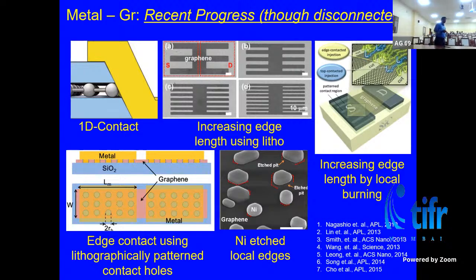Let me also highlight this thread, which later when people had shown that the edge contacts are better compared to the top contacts. While no physical explanation was given, the edge contacts were shown to be better, and of course earlier the low temperature contact resistance was shown to be better compared to the room temperature contact resistance. So the physics world moved into the edge contact and doing measurements at low temperature. Right? I mean, I'm fine. We are getting interesting results.